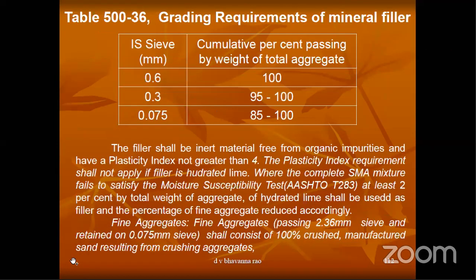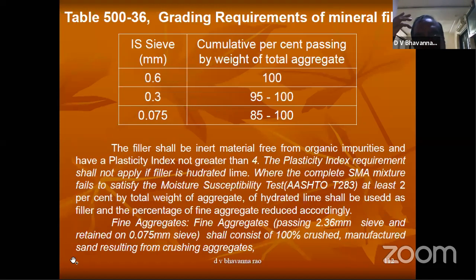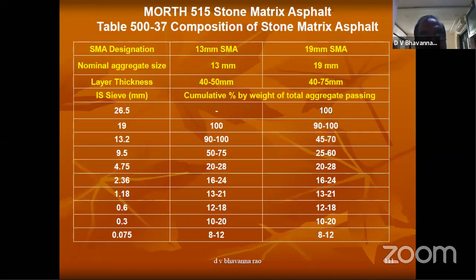These are the gradations for stone matrix asphalt. Two gradations are there. One is for 40 to 50 mm and another is 40 to 75 mm. This is the most effective. This is a very popular specification. In India also, they are using this. It can be used both as DBM and BC. One gradation can be adapted instead of DBM. One gradation can be adapted as BC.